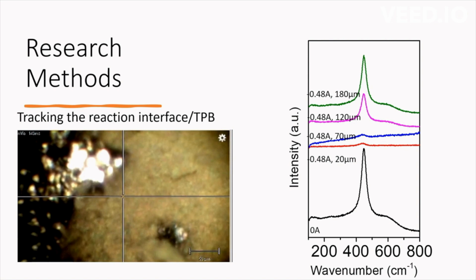the Raman spectra at different distances show that near the interface, on applying negative current density, the catalyst gets reduced. When we go far from the interface, like 70 micrometer far from the interface, the reduction is less. When we go 120 micrometer, the extent of reduction is very little and it's almost oxide. So such type of studies we are carrying out.